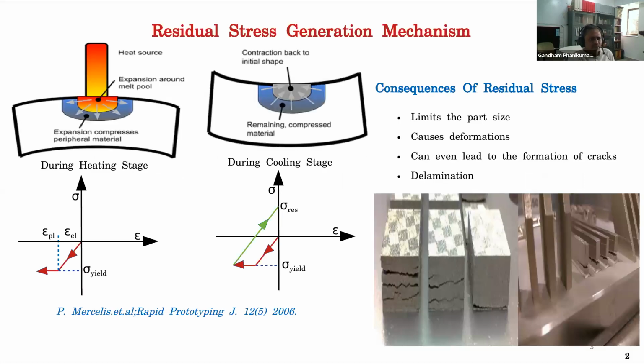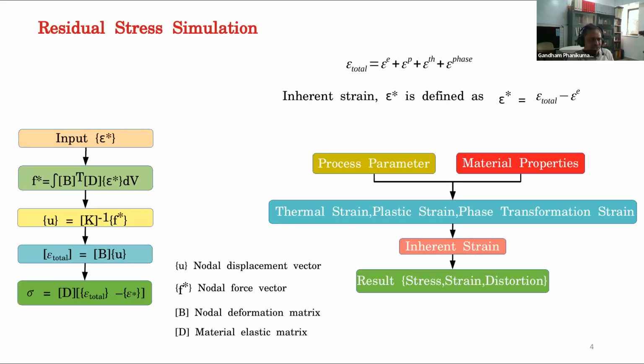So if you look at laser additive manufacturing, you will have problems like this: cracks during printing, and samples coming off from the base plate with cracks going through the component. So they are all attributed to residual stress. And today we have software such as Simufact Additive, which allows you to calculate those residual stresses.